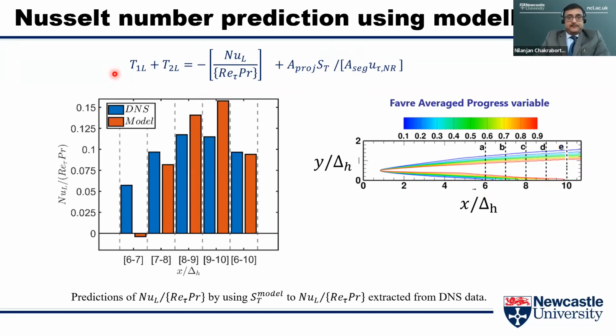One thing to note, based on this equation, it is clear that turbulent burning velocity and Nusselt number are not two independent parameters in flame wall interaction. If you know one, you should be able to find another. T1L and T2L are functions of mean variations of velocity and temperature within the thermal boundary layer. They're relatively easy to measure experimentally. Experimentally, it is relatively easier to measure the wall heat flux. So if one can measure these three quantities, it should be possible to measure the turbulent burning velocity within the thermal boundary layer.